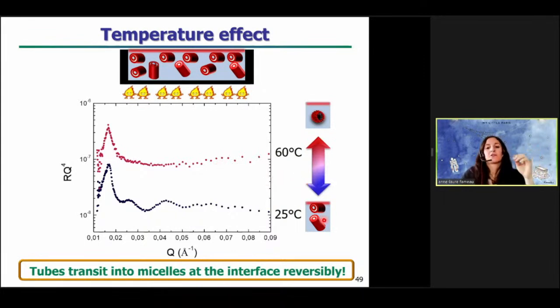That is to say that when tubes are no more present in bulk, when they transit into spherical micelles, they are no more present at the interface. We just have a single fatty acid monolayer. But remarkably, by decreasing back the temperature, tubes are reformed in bulk and they are readsorbed at the interface. So the transition between tubes and micelles is reversible both at the interface and in bulk.